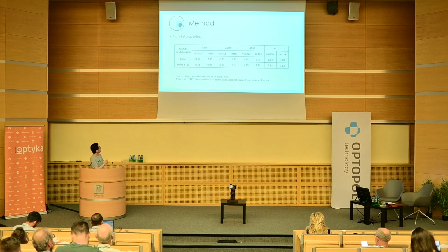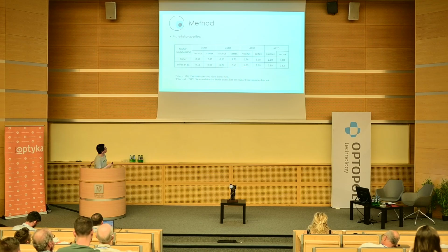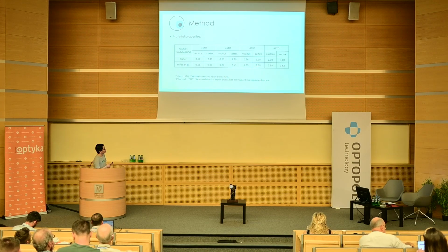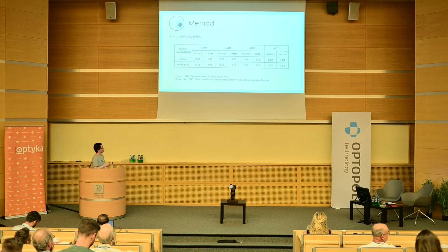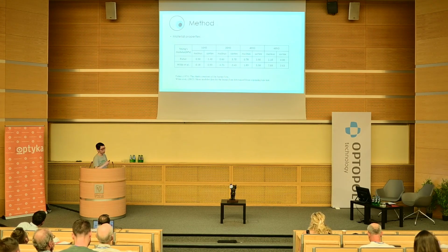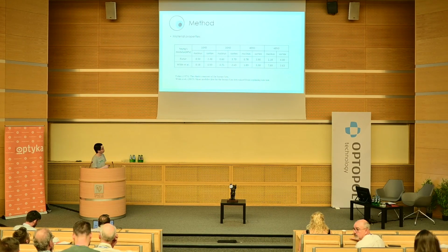But in the data of Waddell, when it goes to 40 years old, the nuclear modulus is about half of the cortical modulus, and after 40 years old, the nuclear modulus gradually exceeds the cortical modulus, and when it goes to 48 years old, it's about twice the cortex.